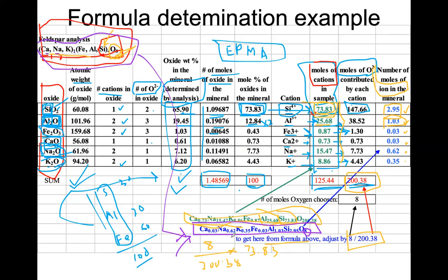You get different numbers. Calcium, for example, 0.03 in this particular case. Sodium 0.62. So these are mole numbers. If you analyze another feldspar from somewhere else, you will again see some different numbers, right? So that is the real solid solution behavior explained by the natural analysis.